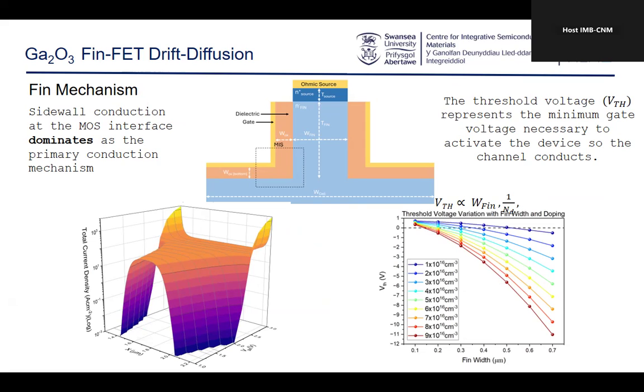this structure, when you turn it fully on. It's a MOS structure, as opposed to a PN junction structure. So this is a dielectric structure here. And we learned from our silicon carbide experience that we need a longer channel length. So we put the oxide down the sidewalls, like before. But what we quickly learned is that when the device is hard on, when it's fully turned on, you get an accumulation layer of electrons down the side.